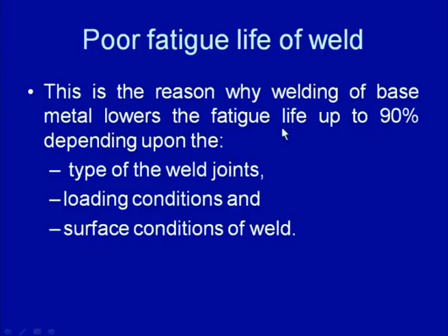the welded joints frequently offer poor fatigue life as compared to that of the respective base metals. And this is the reason why the welding of the base metal lowers the fatigue life of the component by as much as 90% of the base metal. Means the reduction in life can be up to 90% of the life of the component.